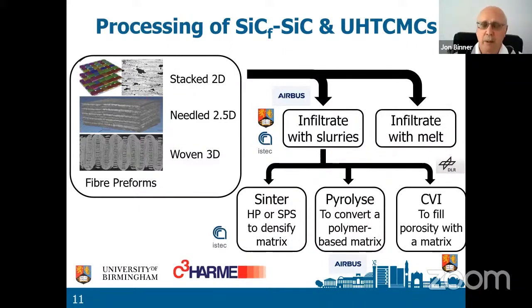And with both of these types of CMC, you can have at least 3 different approaches. So you can use stacked layers of fiber fabric, and that's 2-dimensional or 2D. You can take those stacked layers and you can needle them, and that is when you push literally a needle through the layers, and it picks up individual fibers and pulls them from one layer to the next. So you end up with something in the Z direction. The stacked 2D are all in the XY plane. The needles will have a small amount of fibers in the Z direction. And then you've got the truly woven 3D fiber preforms. The stacked 2D are the cheapest. The needled are a little bit more expensive, and the woven 3D are a lot more expensive.